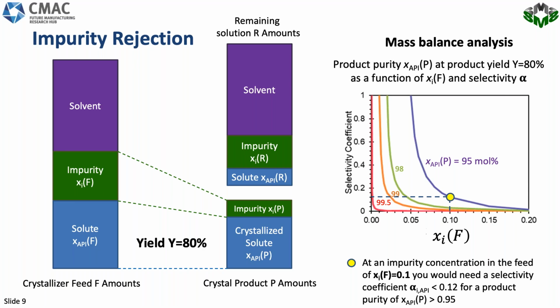Okay. To apply DSC for understanding the eutectic point, what could be the threshold content of an impurity? Is it applicable if the impurity is less than 0.5%? Yeah, DSC is maybe not very accurate if your impurity levels are very small. So then you have to go to another technique to find out whether you have a solid solution or not.